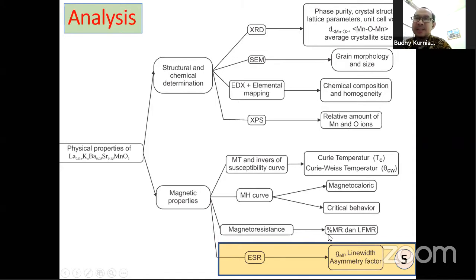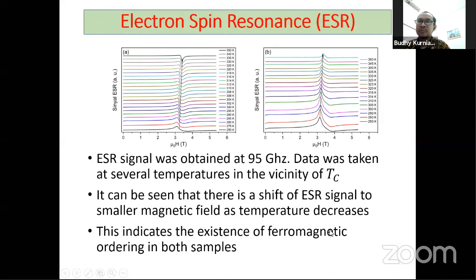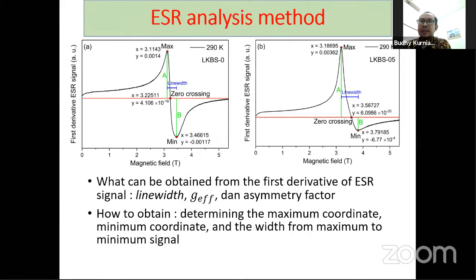And the last is the ESR result. In the ESR result, the important thing is the existence of ferromagnetic ordering in both samples. And we can make some analysis by the line width, G factor, and asymmetry factor.